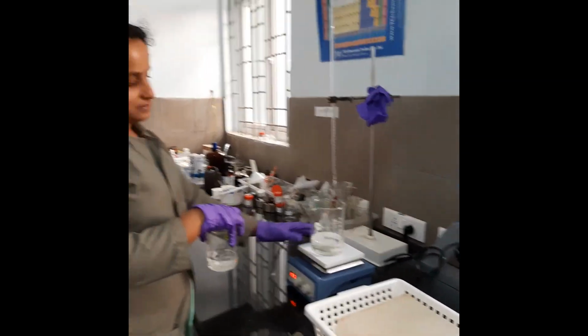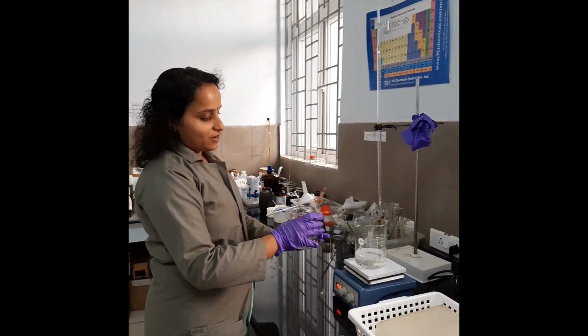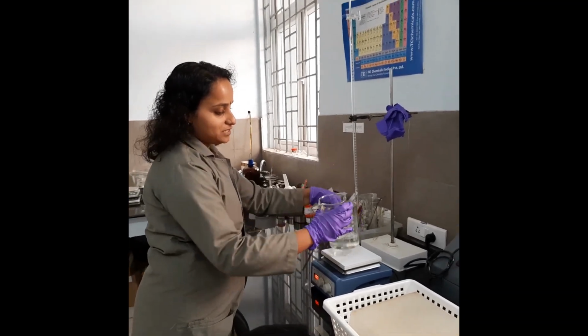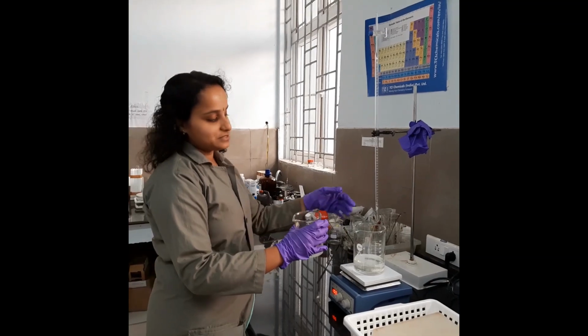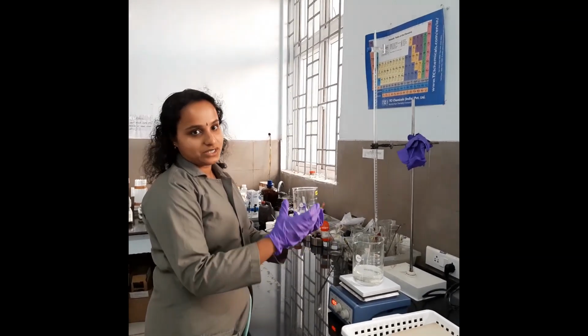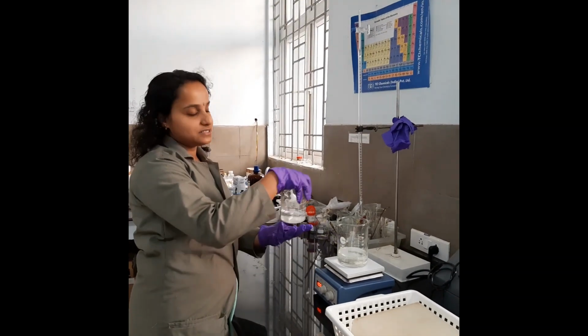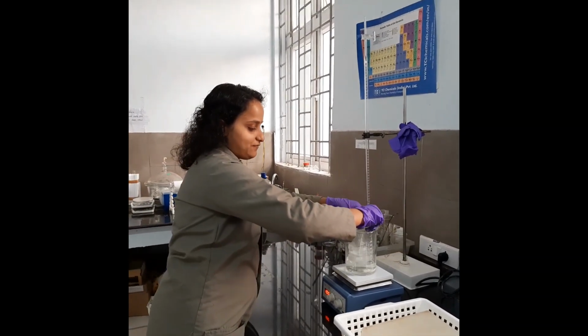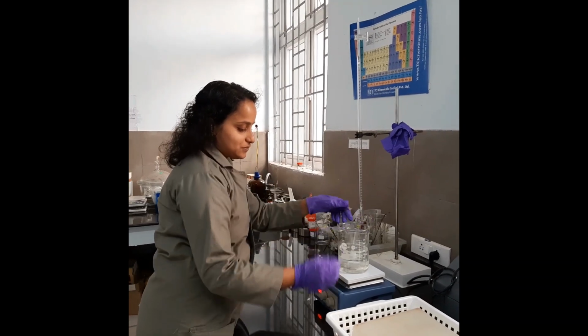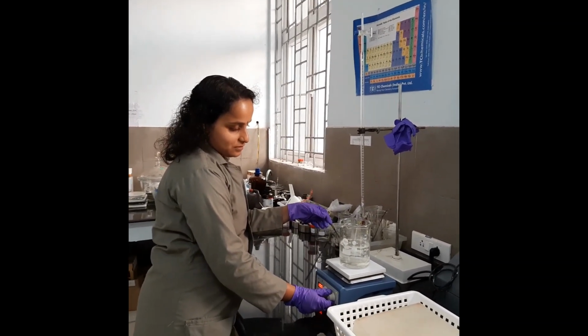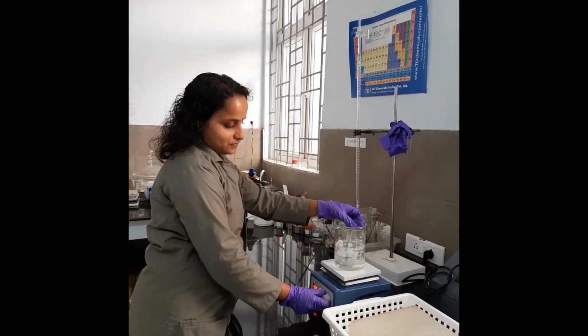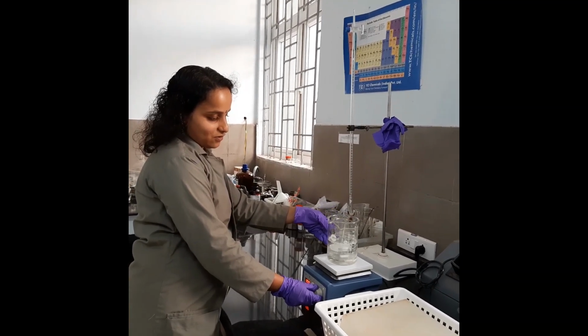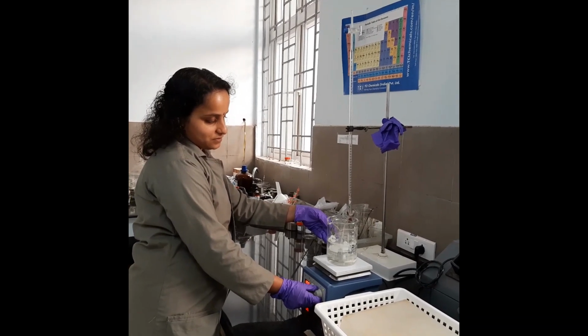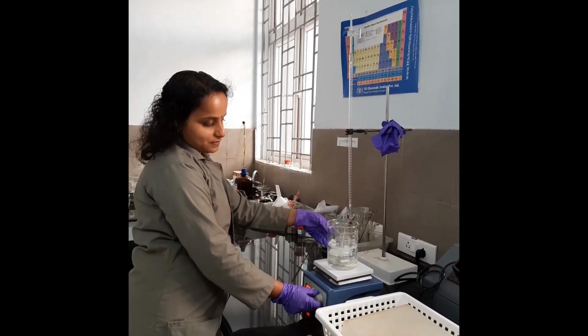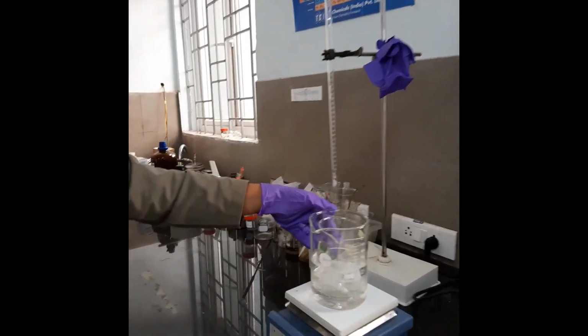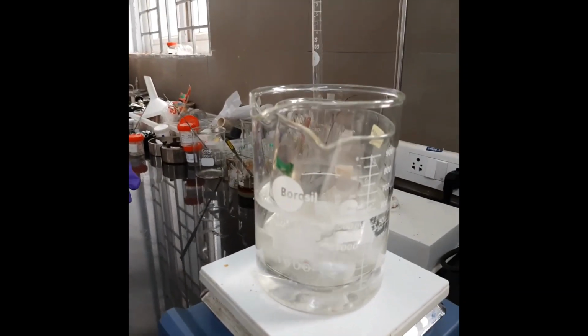So this is a water bath. This is at 65 degrees Celsius. We are not keeping the beaker directly on the hot plate. Why? Because we need uniform distribution of temperature in our solution. That's why we are immersing this beaker into a water bath at 65 degrees Celsius. Then we are allowing the solution to stir gently. We can see that all the salt is dissolving immediately in water. It forms a uniform, colorless solution.